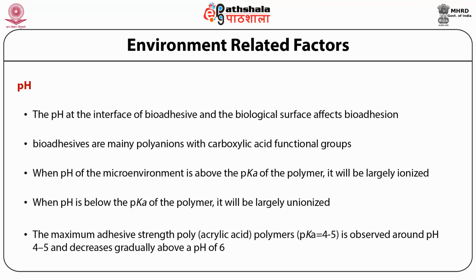The maximum bioadhesive strength of polyacrylic acid polymer is observed around pH 4 to 5 and decreases gradually when it is above pH 6. There are numerous investigations which have shown that the carboxyl groups which are protonated, rather than the ones which are ionized, react with mucin molecules by forming hydrogen bonds with it.